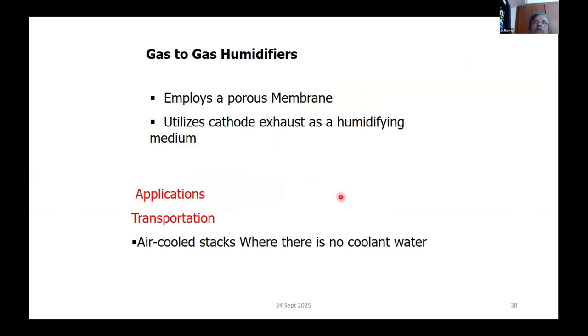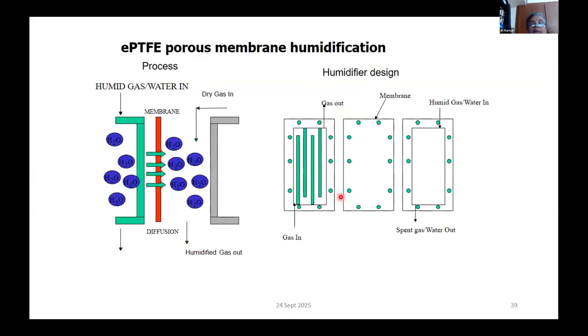Another thing can be a gas to gas humidifier. In this, the oxygen side is where the water is produced. So you have that water rich outlet gas passing on one side. On the other side, you have a dry gas, and you use a porous membrane. So water will diffuse across this porous membrane and the gas will be humidified. This is meant basically for an air cooled stack where there is no coolant water available. The water moves across the membrane, and the dry gas gets humidified and you get a humidified gas actually.